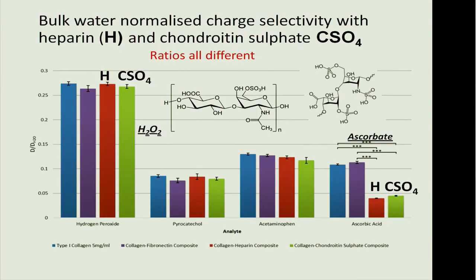Okay. This is heparin, this is chondroitin sulfate, and they're charged species. That's fine. That's all I need to tell you. And you're back to the depression of ascorbate diffusion through heparin and chondroitin sulfate polymer. And this time, these are ratios. Again, as I've shown you, zoom down permeability, you zoom it down, but here it's starting to get charge-based selective, and here this ratio and this ratio and this ratio, I go back to my point, should not be different.